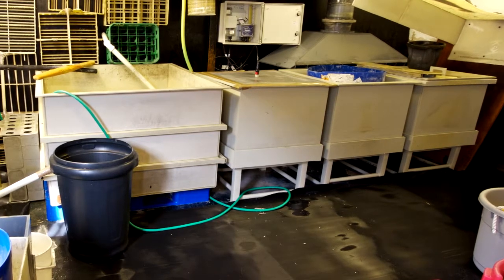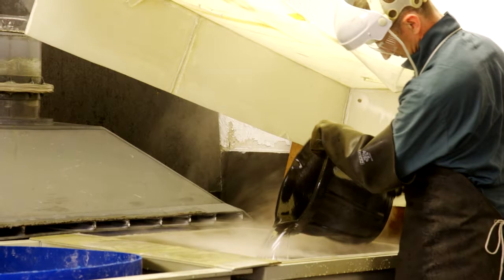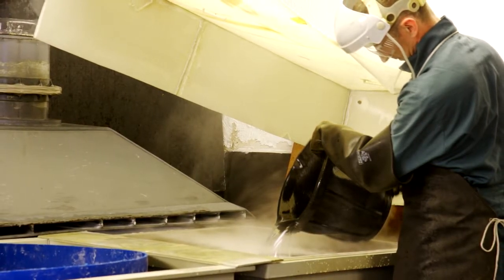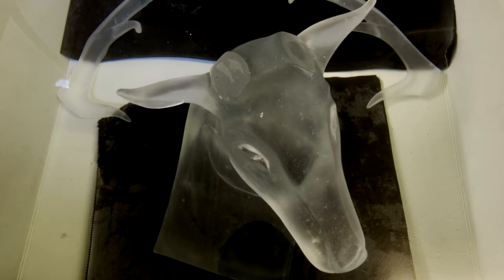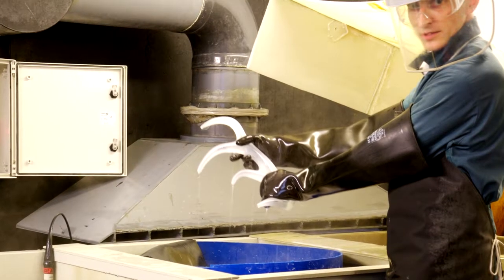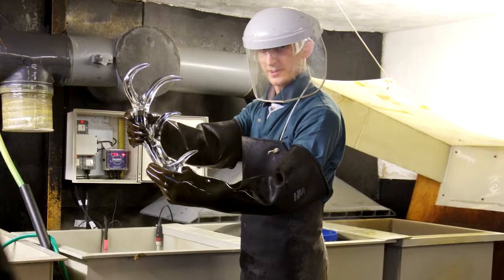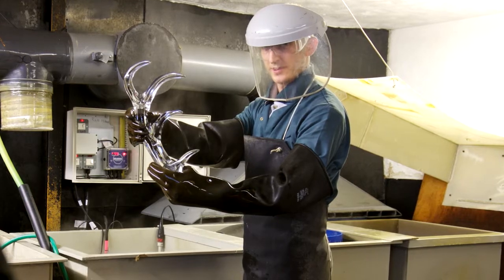So the acid polishers have a big bath which is filled with hydrofluoric acid. They preheat the stag overnight in a bath of water, because the acid itself is quite warm. So to even up the temperature, they preheat it gradually overnight to about 65 degrees, and then the next day they take the stag and they move it straight from the water bath into the acid. They leave it for about 20 minutes in the acid bath. They rub it all over the stag, and miraculously the stag comes out completely shiny. The antlers go through the same process again.